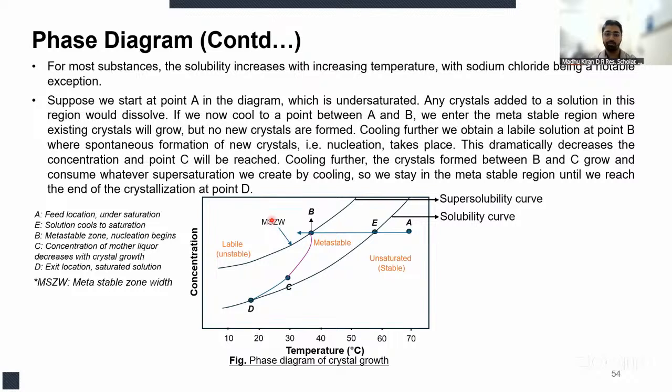Generally, this kind of behavior is seen, and also the size distribution will be very wide, because a few crystals might have grown to a larger extent, and there might be a few crystals which have not grown at all. You can get a size distribution anywhere between 50 micrometer at D10, and then D90 might be maybe 700 to 800 microns.